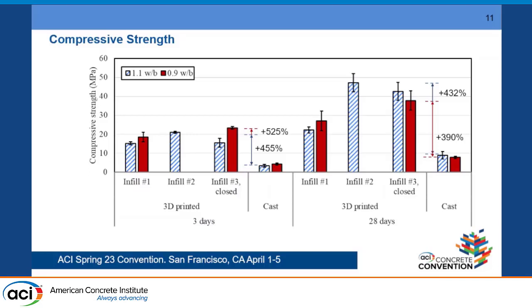And at 28 days, we see that we are still gaining a significant amount of strength. Now, the water to binder ratio here is much higher than what you typically would expect with cement, and that's what makes it rheologically more difficult to 3D print. But we can see here that at 0.9 or 1.1 water to binder ratio, we are gaining a significant amount of strength. In some cases, we can gain strength up to 50 megapascal, and that's quite sufficient to use this as a structural material to build with.